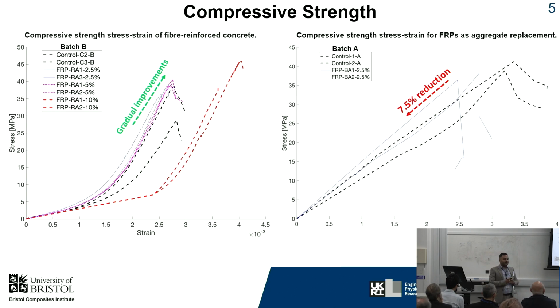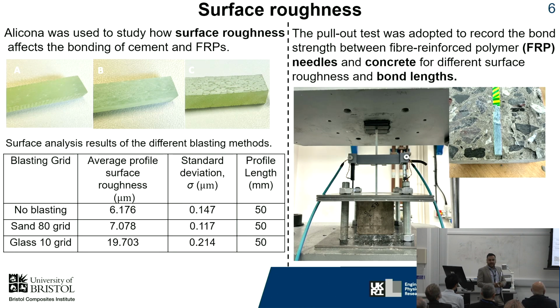This is one of the key findings of my PhD, because the majority of the literature shows a reduction in compressive strength, and that reduction was the second key element for me to move forward with my PhD. I was always wondering why we always have a reduction in compressive strength, in my work and in the literature, from other researchers. The key element here is that the surface bonding between the needle itself, the GFRP, and the cement is very poor.